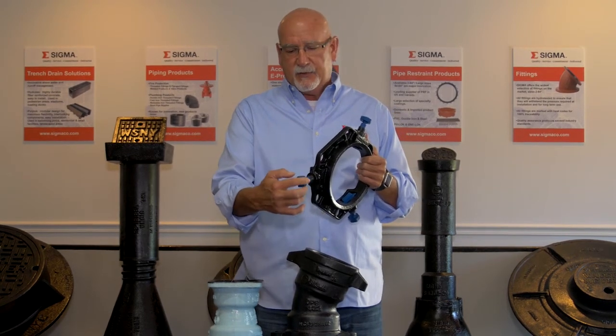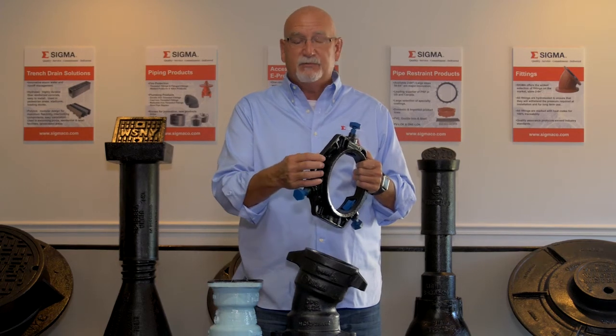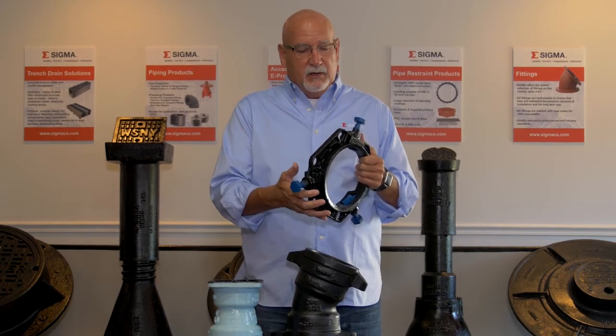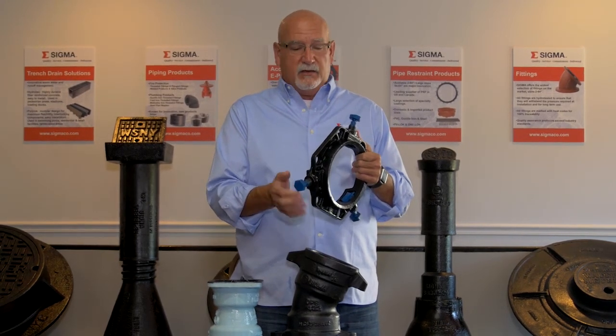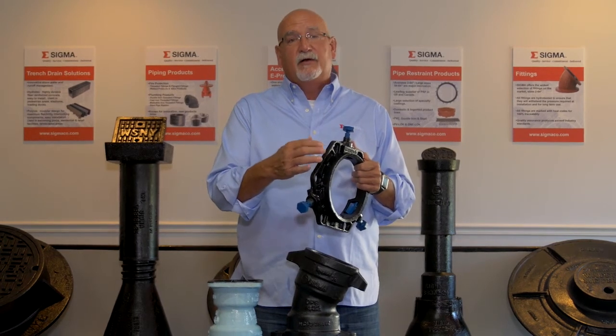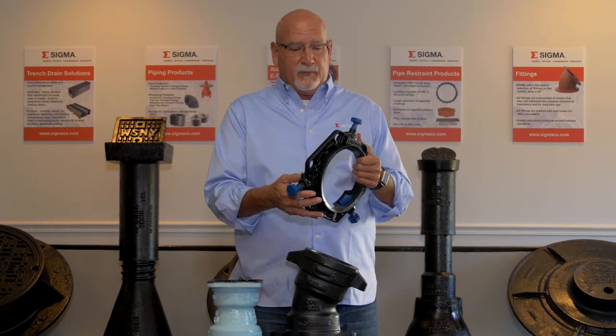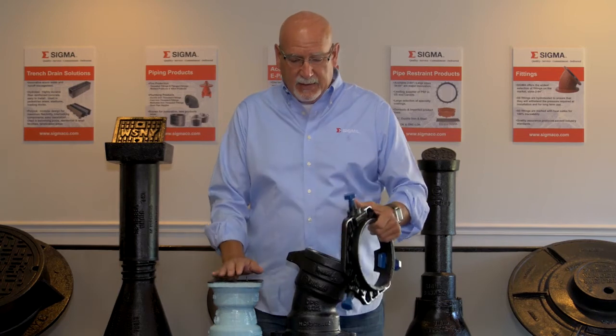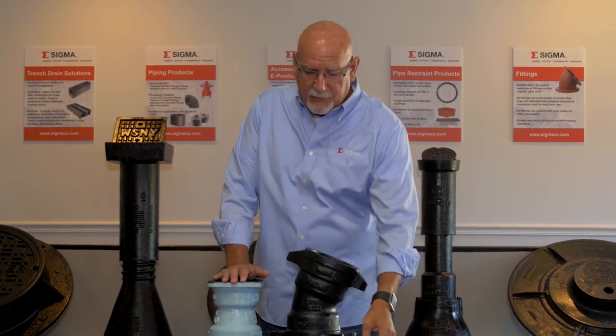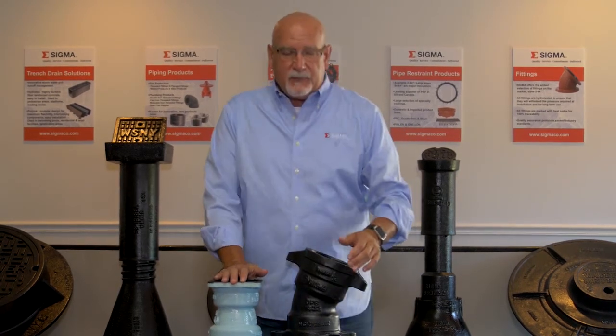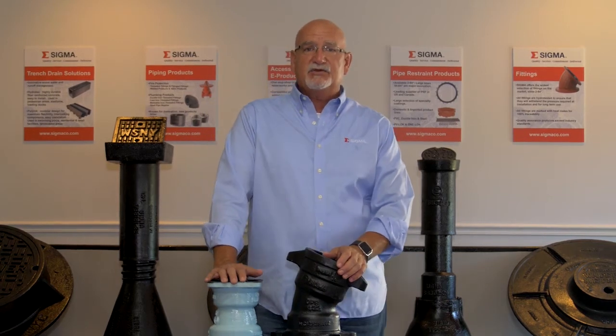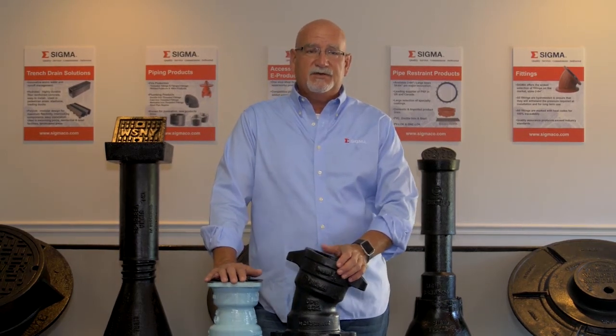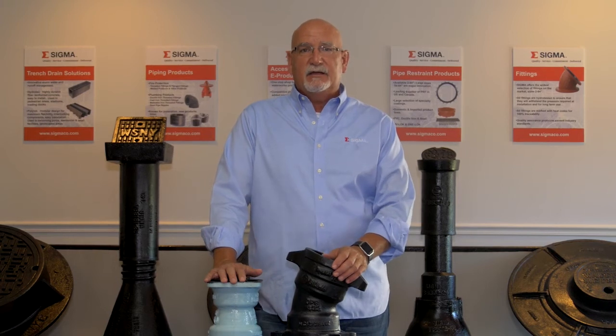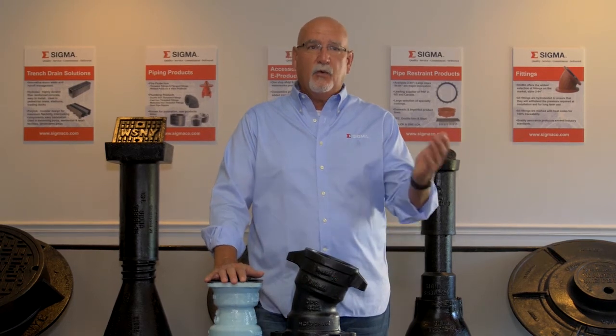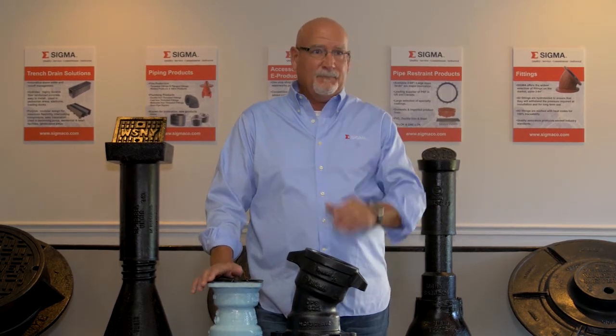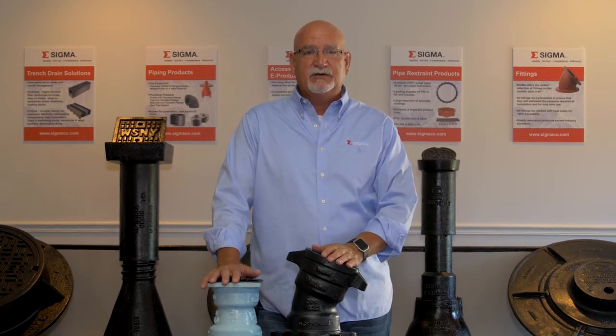This top coat happens to be blue, this top coat happens to be black, and if this were a PVC restraint, the coating would be red on top of the black E-coat. So E-coating, when you compare it to other types of coatings in a side-by-side salt spray test, which is the mechanism that is used to compare one coating to another, a little basics about salt spray.